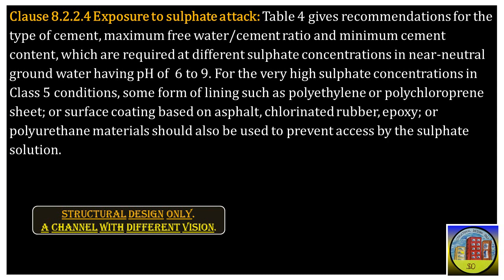Table 4 provides recommendations for the type of cement, maximum free water to cement ratio, and minimum cement content necessary at different sulfate concentrations in near neutral groundwater with a pH of 6 to 9. In cases of very high sulfate concentrations in Class 5 conditions, it is advisable to employ some form of lining such as polyethylene or polychloroprene sheeting, or surface coatings based on asphalt, chlorinated rubber, epoxy, or polyurethane materials to prevent access by the sulfate solution.